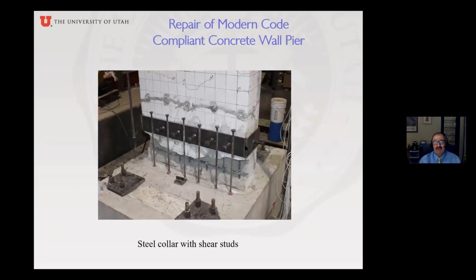Sometimes the grout doesn't bond very well to the original wall concrete, so we build this steel jacket or steel collar and we put some studs on it. So the concrete grout that goes in here will actually bond to the concrete. So for example, the wall had a compressive strength of 5,000 psi, and the grout ended up being close to that, about 4,500 psi. So sometimes they won't bond automatically. So if you do this collar, it's not that difficult.